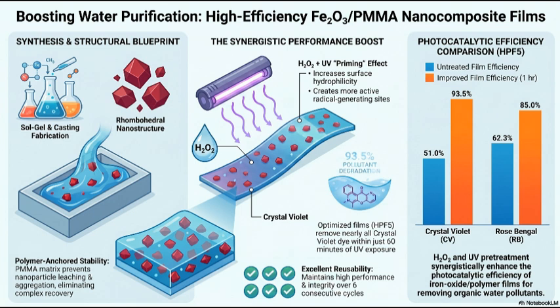Exactly. Meanwhile, the electrons that were catapulted up to the conduction band interact with the dissolved oxygen in the water to create superoxide radicals and eventually generate more hydrogen peroxide within the system. So the dye molecules are caught in a crossfire between hydroxyl radicals and superoxide radicals. It is a systematic demolition. These radicals rip the molecular bonds apart. They shatter the complex rings of the crystal violet and rose bengal molecules into smaller, unstable aliphatic acids. The radicals then attack those smaller acids, breaking them down further and further until the entire structure collapses into nothing but H2O and CO2. The threat is completely mineralized.